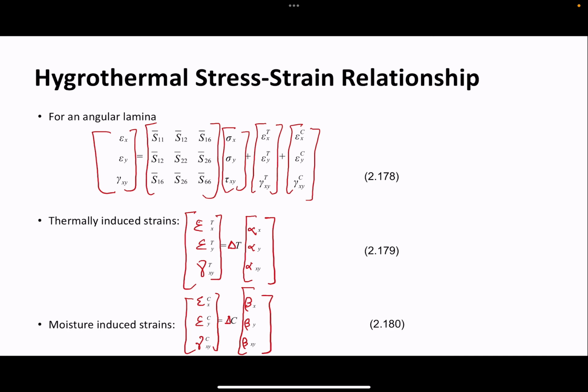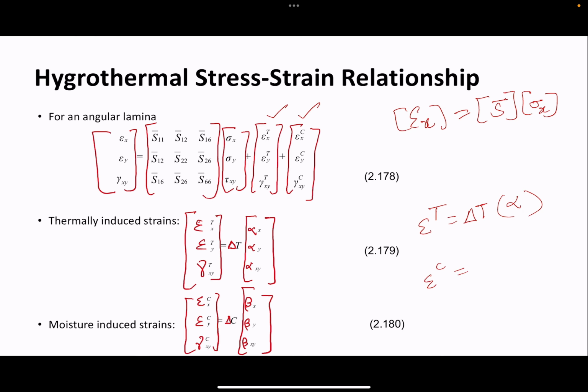So then if you bring in an angular lamina, it gets more complicated, because we know global strains are equal to the transformed compliance matrix S bar multiplied by your global stresses. So again, here you have two additional components, thermally induced and moisture induced strains, but they're also in the global dimensions. So how do you get them? Thermally induced strains again is temperature change multiplied by your alphas, the coefficients of thermal expansion. And then your moisture induced strains are the amount of moisture absorbed multiplied by your betas, which are the coefficients of moisture expansion. But these are also in the global directions.